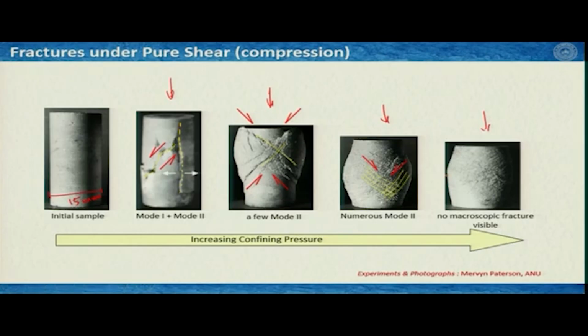With a little more increase in the confining pressure, we see that mode 1 fractures are gone from the system, and we mostly see mode 2 fractures in two different sets. One set is like this, another set is like this. With further increase of the confining pressure, we see numerous mode 2 fractures, as you can see here from these little yellow dotted shades.